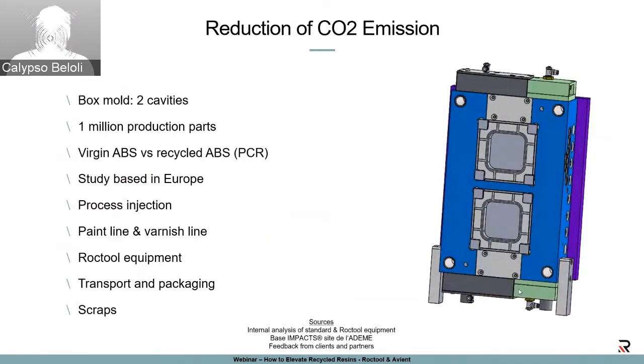Another very important point is the CO2 emission, as I said before. And here we have done a very interesting study with our box mold, 2 cavities. And the idea is to evaluate the CO2 emission in the conventional process versus Roctool technology. For this study, we take into account 1 million part production. You will see a comparison between standard or virgin ABS and PCR ABS. The study has been based in Europe, and you will also see the impact of the decoration, paint line, varnish line. We take into account the Roctool equipment, the transport, packaging, and of course the scraps.